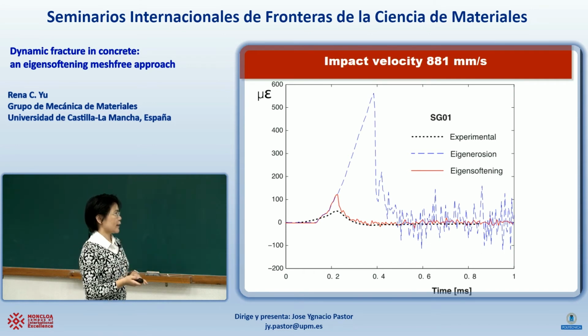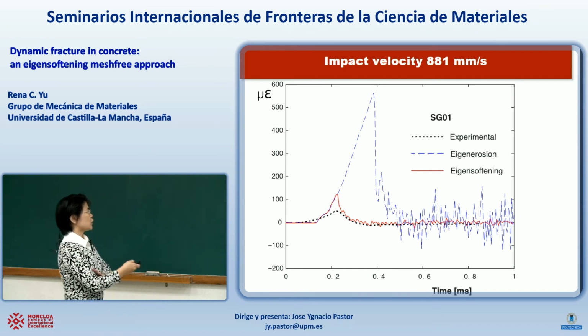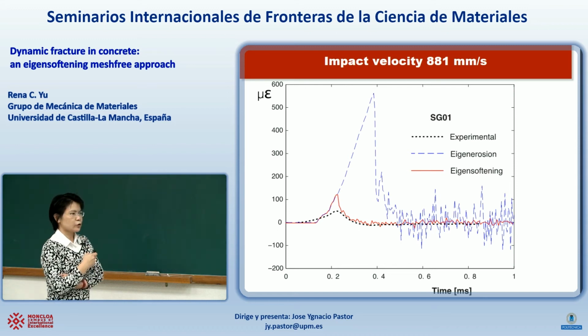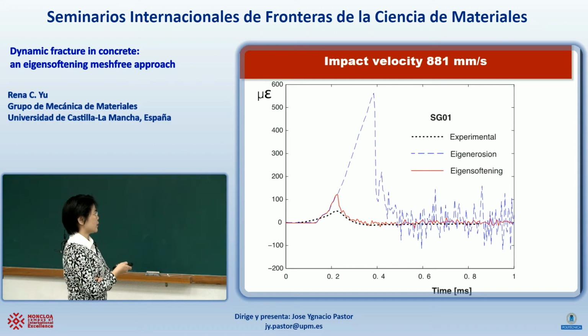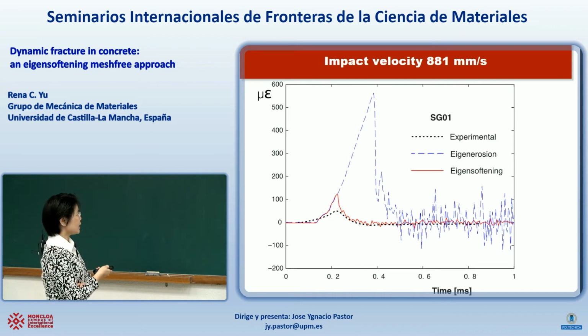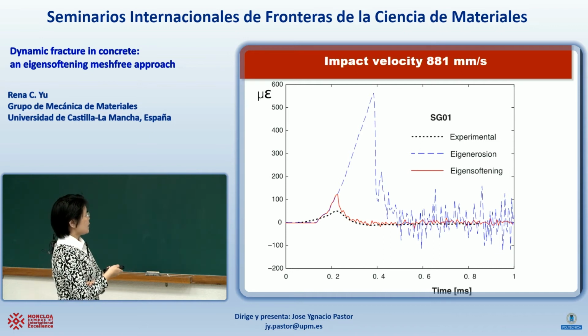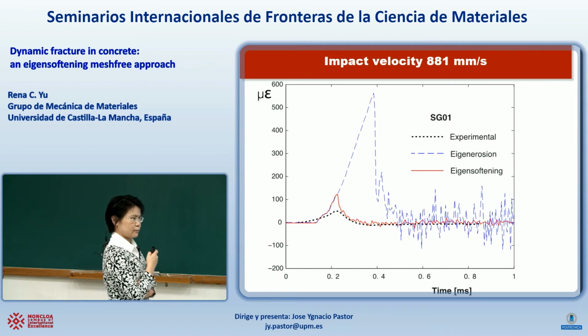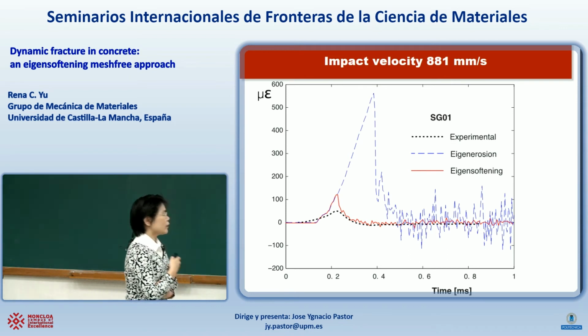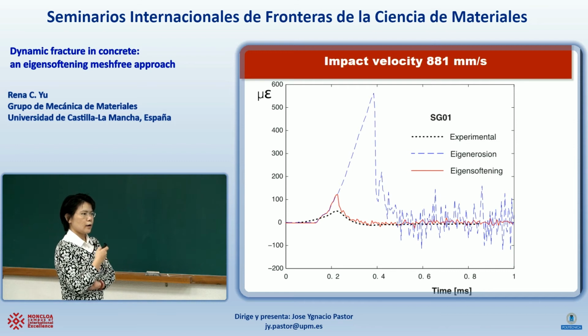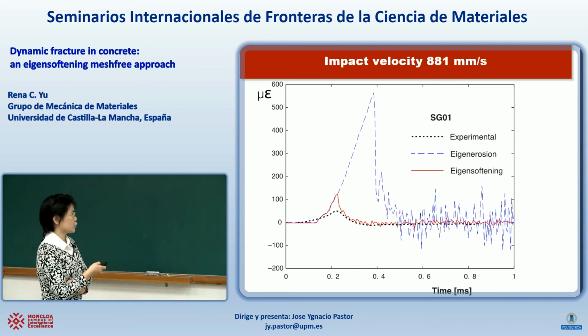since concrete is not that homogeneous, we might not trust the numbers completely. Actually, we use the strain gauges only to try to see where the peak is. But in any case, if this is 2 times or 1/2, it does not matter that much. But in this case, it gives almost 10 times more strain. So that means that locally, the stress was being overestimated because of the energetic criteria that was used for the eigenerosion approach.